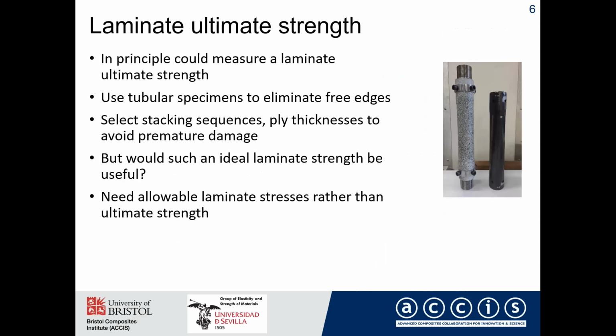Now, in principle, we could come up with a laminate ultimate strength. We could use tubular specimens, for example, to get rid of free edges. We could select the stacking sequences, the ply thicknesses to try to avoid premature damage. But even if we could really do that, would that ultimate ideal laminate strength be useful? I'm not sure. And I think this is one of the things that causes perhaps a bit of confusion: why do we want this strength parameter? Is it to know the ultimate strength of the material and as a reference point, or is it something we want to use in design?